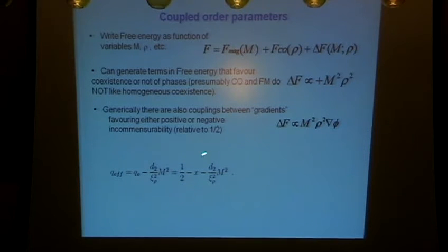And if this bare q value is the thing you expect in terms of the charge order, just from chemistry, so this goes like half minus x with doping, and then I have this term there, with a coefficient whose sign I don't know. But once you pick the sign, and let me assume the sign was positive, then what you see is that it's possible to have this term for magnetization cancel out this term from chemistry. So what I can do is make the wave vector stable at a doping of a half, providing it's also magnetic.